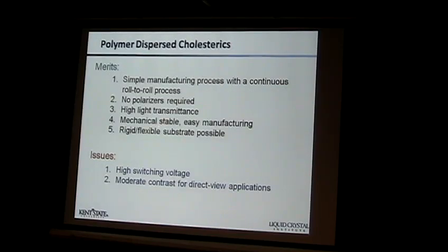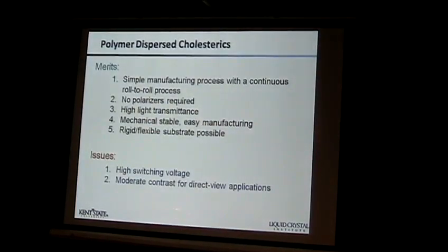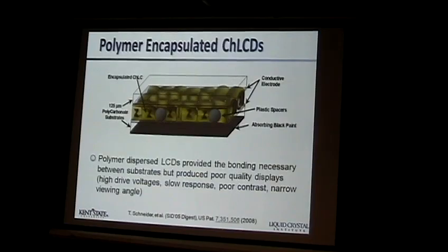They are stable and easy to manufacture. They are rigid or flexible; we choose a substrate. The only concerns are the driving voltage if you mix polymer with low molecular weight liquid crystal. They also sometimes deteriorate in contrast when the phase-separated polymer is mixed up with the helix. So in general, I think this morning you wanted to show the issue, so we can skip this.